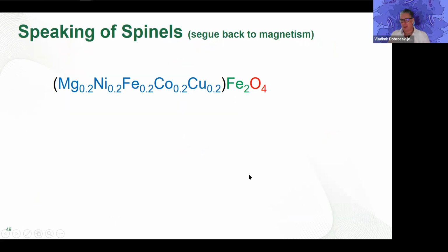In some of these structures, you may not have long-range order, but you can have substantial short-range order. To follow up on what Marcus is saying, it's not completely random, provided that this electrostatic energy is much larger than the thermal energy. But getting long-range order in any periodic structure could be very difficult to achieve, so the type of short-range order may affect physical properties.